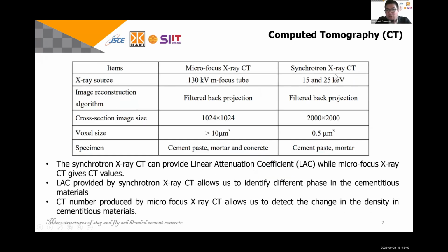The difference between microfocus X-ray CT and synchrotron X-ray CT is especially in the focal size. In microfocus X-ray CT, the minimum focal size up to now is maybe around 10 micrometers, but for synchrotron, we could achieve 0.5 micrometers. So a very small microstructure size can be resolved by synchrotron X-ray CT. But again, the drawback: if you try to achieve a smaller voxel size, you have to prepare a smaller sample.